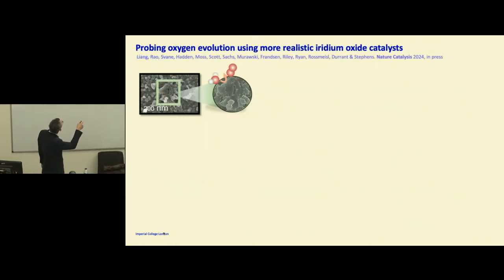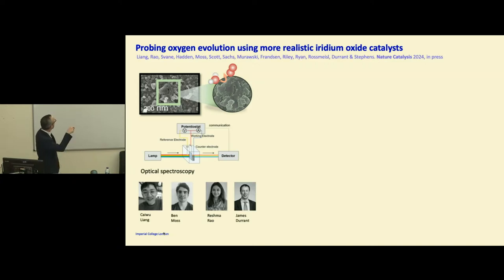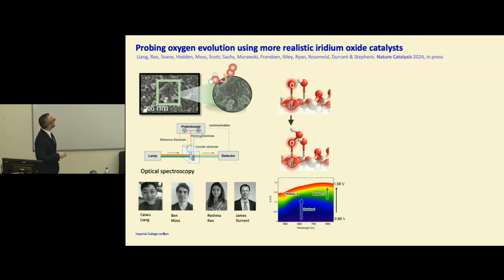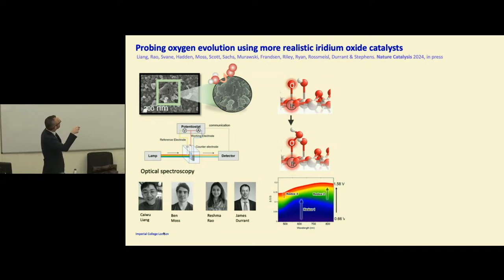This is a typical example of the iridium oxide catalyst that we use. You can see that this is a microscopy image, and they're quite rough. Luckily, I'm partnered up with James Durrant, Reshma Rao, Ben Moss, and Calex Liang, a PhD student who's in the audience as well. James' group are experts at spectroscopy, basically shining a light through the sample and seeing how it changes as a function of applied potential. So we got this really nice spectra. I won't go into detail what it means exactly, but what we can tell from it is how strong the binding of oxygen is to the catalyst surface. And as I mentioned previously, that's what we think controls the performance.